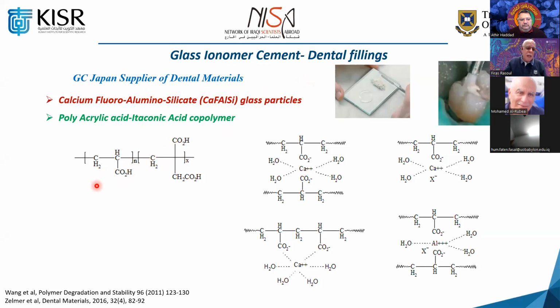And this material is basically a copolymer of acrylic acid with itaconic acid. So these two types of monomers copolymerize randomly and are mixed with fine glass particles. It's called calcium fluoroaluminium silicates. And when they mix with it, they form some sort of a salt bridge because of these acid groups. So they form a salt bridge with the calcium, they form a salt bridge with the aluminium, etc., etc. So they are curing by this technique.